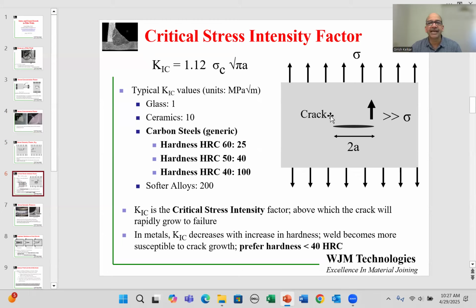Now these are the typical stress, and I'm showing you here in the schematic form, the applied stress, the crack of length 2a, and that a goes into this formula, and the overall applied stress goes over here. Now, typical stress intensity values with the units of megapascal square root meter are shown over here. Glass has a value of 1 because glass is extremely brittle, and even the tiniest of cracks with very simple loads can lead to failure, as I'm sure you are familiar with. So glass has a value of 1. Ceramics have a value of 10. So ceramics are stronger than glass. That's why the K1C value is greater, even though ceramics are also quite brittle, but their bond strength is much greater than typical glass. So that's why ceramics have a bigger number.